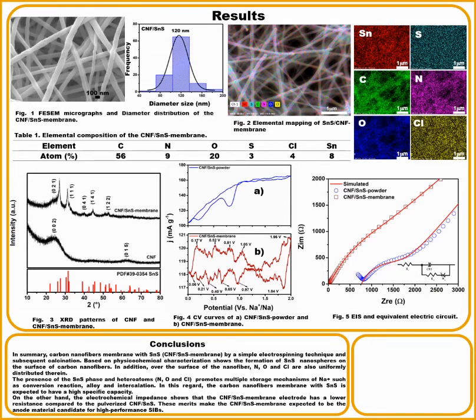In conclusion, the carbon nanofiber membrane with tin sulfide was made by a simple electrospinning technique and subsequent carbonization. Based on the physicochemical characterization, it shows the formation of tin sulfide nanospheres on the surface of the carbon nanofibers. In addition, over the surface of the nanofibers, nitrogen, oxygen, and chlorine are also uniformly distributed. The presence of the tin sulfide phase and other atoms promotes multiple storage mechanisms of sodium ions such as conversion reaction and ion intercalation.